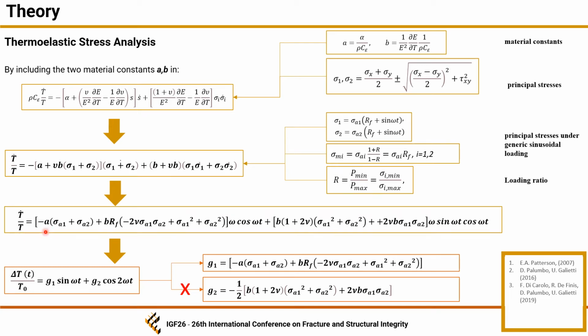the thermoelastic temperature variation as a function of the material constants A and B, Poisson ratio, and the amplitude of the principal stress in direction 1 and in direction 2. And this equation, in a more compact form, represents the general expression of the thermoelastic signal in proximity of the crack under the hypothesis that the temperature variations are very small compared to the environmental temperature.